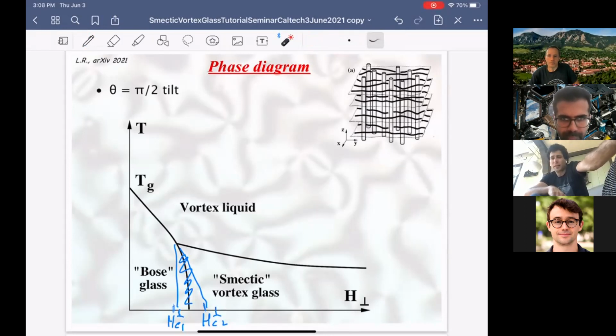And is there a concern about, in type 1 superconductors, when there's this mixed state where some region wants to become normal? Is there a concern about that possibility of getting a mixed state here? Well, this is a strongly type 2 superconductor, so I'm considering the strongly type 2 limit. It's not normal to get any mixed state. It's just this unusual state which can propagate in one direction. But there's anisotropic resistivity. It feels a little bit like a mixed state, but it's not mixed in space. It's just mixed in dimensionality.